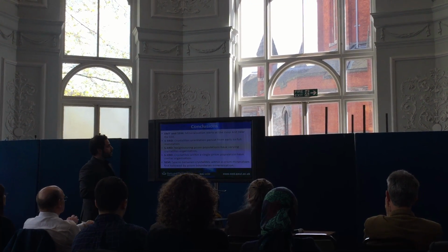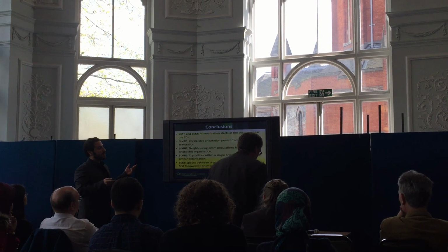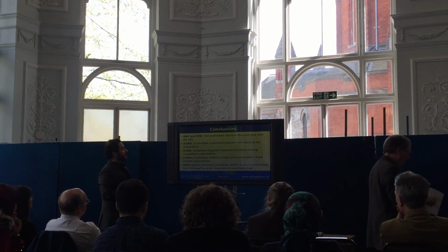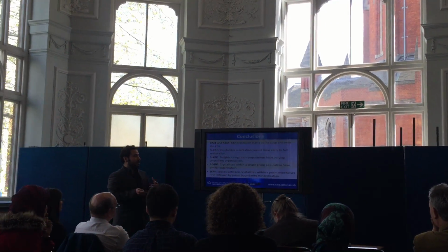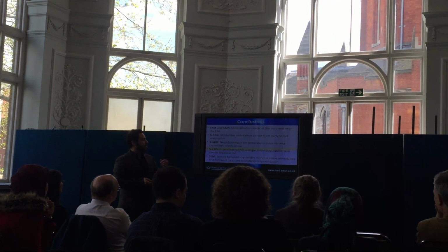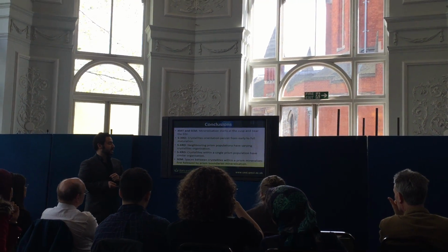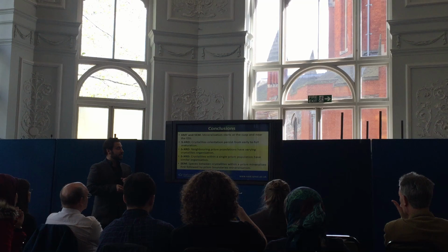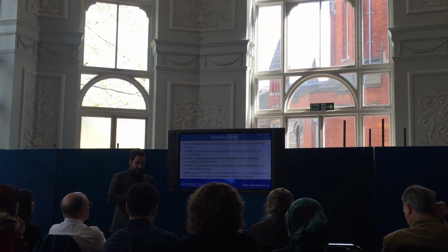And to conclude, we found that mineralization started at the cusp near the EDJ. Crystallite orientation persists from early through to full maturation. Neighboring prism populations, as I have said, have varying crystallite organization, while crystallites within a single prism have similar organization. And the spaces between crystallites within the prism mineralize first, followed by prism boundary mineralization.